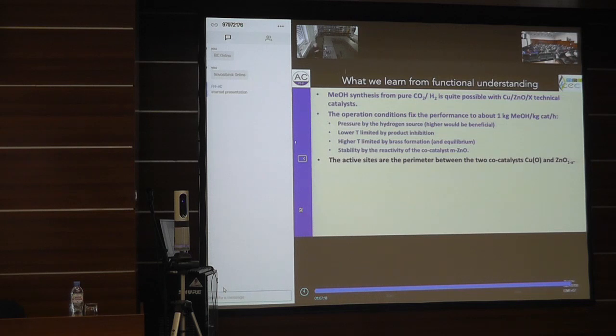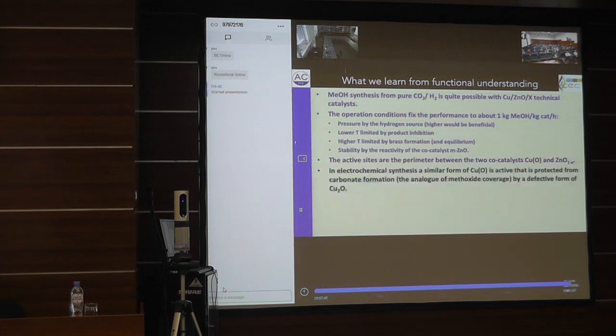You can have it even that there are little patches of zinc oxide that are moving around, or you can put a combination of zinc oxide crystals in close contact to copper crystals that do not overgrow, but you still have a perimeter. It doesn't matter, both ways work. It works in both types of catalysts, which also exist under industrial conditions. I did not show that; that was the part that I was overdoing because I think this is too much for now.